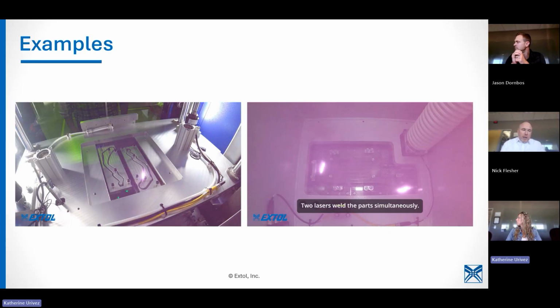anywhere between a 0.5 to 2.5 millimeter weld rib width. We can do wider. Our laser path can actually be up to 25 millimeters wide. That's a big beam spot. We can do that large. And we can do flat to flat, but we don't recommend it. There are some part variation issues that come into play. You need force. Catherine said you need force. What you actually need is pressure. And so having a sacrificial rib allows you to get more pressure into the weld joint with less force.